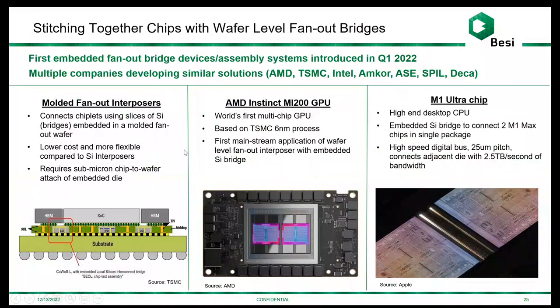And then another use case, or another layer in the interconnect hierarchy for these chiplets, is bridge die or fan out die. And this is typically used in the cases you see on the left of a fan out interposer as an example, where you have a molded wafer with embedded chips, and those embedded chips can be bridge die or local silicon interconnects, as TSMC would say. These need to be placed with very high precision in a die face up or face down configuration in a fan out process flow. So it requires high precision chip to wafer bonding, but in a face up orientation typically. This is being used in high volume production now.